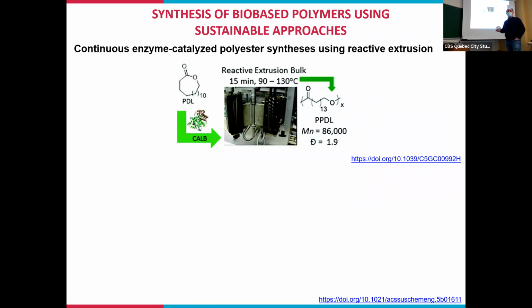This is the first example that we have shown, to carry out an enzymatic polymerization. Enzyme is like a catalyst, but very sensitive to temperature. And when you try to apply it in a batch, in organic solvent, or if you use a very long polymerization time at high temperature, like the temperature you can have in the case of extrusion, you can have loss of activity.